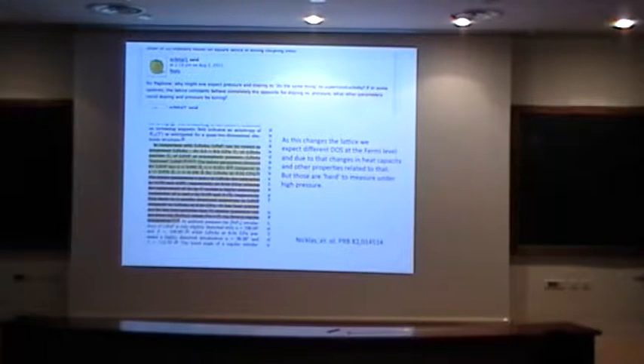And if we take that a step further, and we think, okay, we change the lattice constants, and we do a band structure calculation on that, what we get is basically a change in the density of states at the Fermi level due to the change in the parameters. And so the density of states is linked to a couple of things that we can measure: heat capacity, resistivity. Usually we refer to resistivity because that's the easiest to measure under pressure, because heat capacity is very hard, if not impossible; I don't know of any paper measuring heat capacity under high pressure. But there are certainly other possibilities to see that. Did that sort of answer the question?